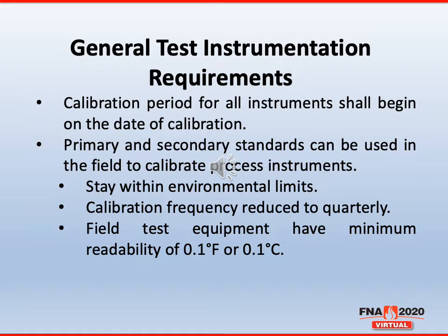The one thing we do hold back on is that the calibration frequency for those test instruments, if they are brought out onto the shop floor, would be reduced to a quarterly interval. For instance, a primary standard, if it stays within the laboratory, the calibration interval is 3 years. A secondary standard's once a year. But once those are removed from the laboratory environment and brought into the field, the calibration frequency drops to quarterly.